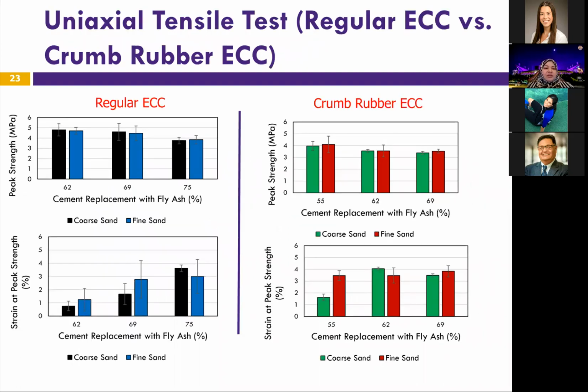This is a slide that shows some of the uniaxial tensile test results of regular ECC and crumb rubber ECC. An improvement was observed in the tensile ductility when we used the crumb rubber. We used 20% crumb rubber and it improved the ductility. With respect to the tensile strength difference between the coarse sand and the fine sand, as you can see, it was negligible. However, the use of fine sand enhanced the ductility.